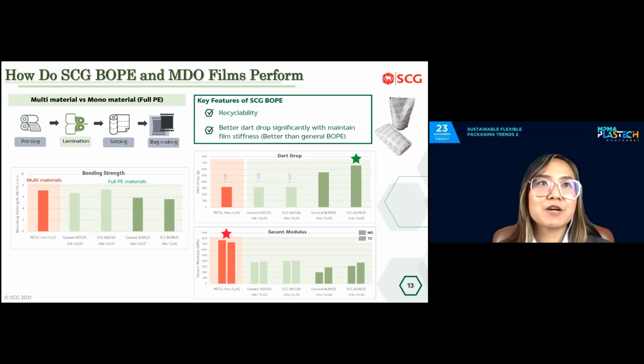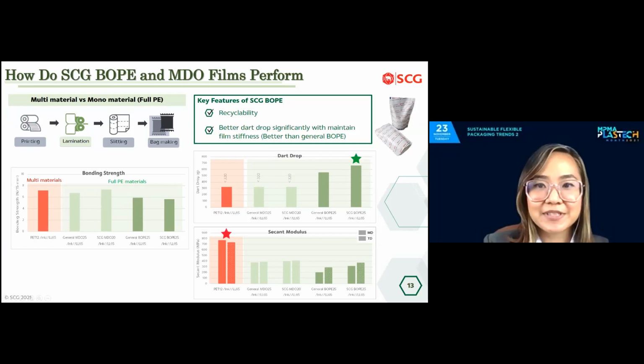So what about the performance on the lamination? Comparing the monomaterial full PE to the multi-material packaging containing PET, it's very clear that some properties could be better or equivalent, but some properties could not be the same. It can be solved by the structure design to support the monomaterials packaging. The SCG BOPE can provide high heat resistance and also lower thermal shrinkage. And also you can see here, we can give higher dart drop compared to the conventional PET printing layer